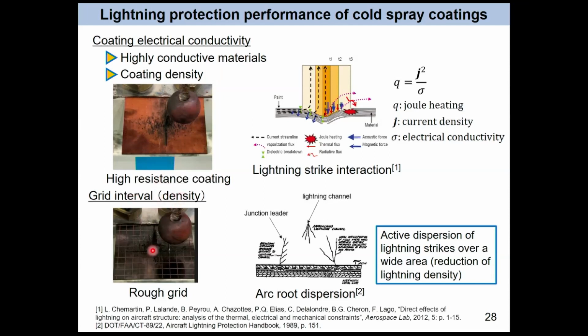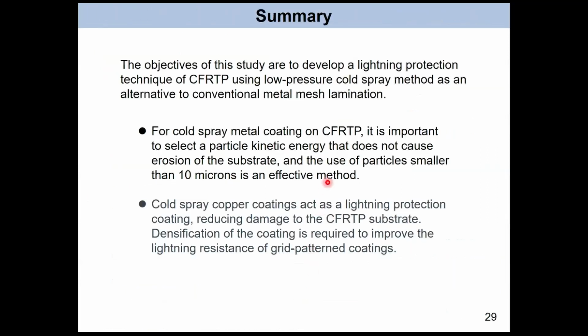And grid interval is also important. When using rough grid patterns, we cannot protect the CFRTP either. Electrical conductivity has a very strong relation with Joule heating, so improving conductivity is very important. Also for the grid pattern case, we have to design to improve the arc dispersion phenomena. Expanding the arc root and reducing the current density on the CFRP is really important.